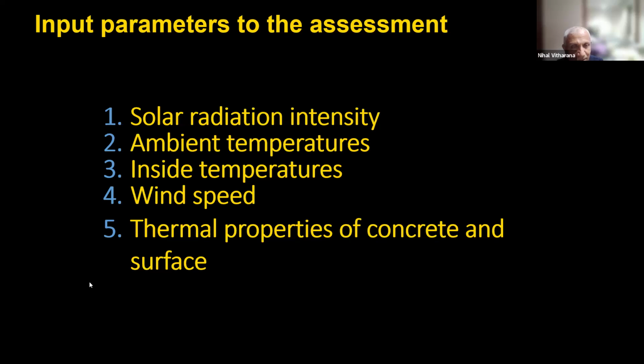So the temperature gradient assessment needs some key input parameters. Of course, solar radiation. Then ambient temperature. If ambient temperature increases, it sets up a temperature gradient as well. Inside temperature, as I said, the gas phase digester has artificial heat to 36 degrees, whereas a concrete tank in Australia, even in summer, temperature would be about maximum 18 degrees. Then wind speed: the higher the wind speed, the more it takes away heat from the heating up wall. It's called convection.